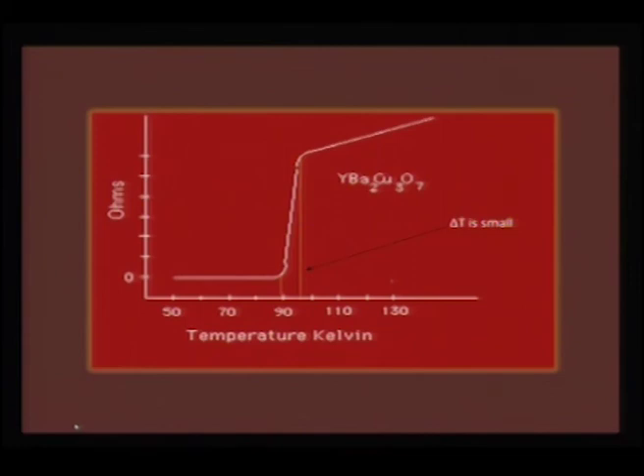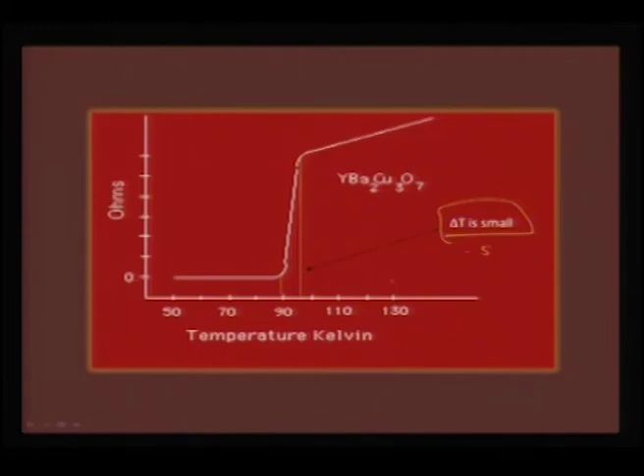Typically this 123 compound shows a very excellent transition, and the onset is somewhere around 93 K, and it goes to an absolute zero resistance state as close as 90 K. If you look at the delta T, it is very small, and this transition shows that the whole sample is superconducting, and it is not a biphasic compound, it is a monophasic compound. As a result, the delta T is very narrow, of the order of just 3 to 5 Kelvin, and the smaller the delta T, the more you can be sure that your whole compound, the bulk, is actually superconducting.